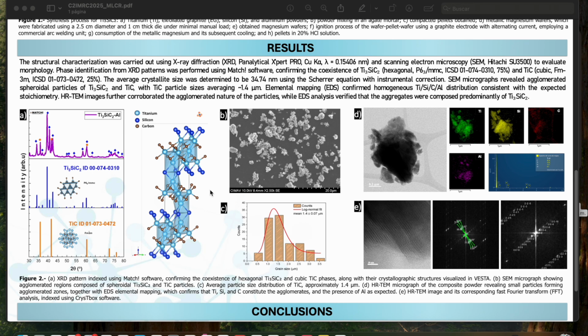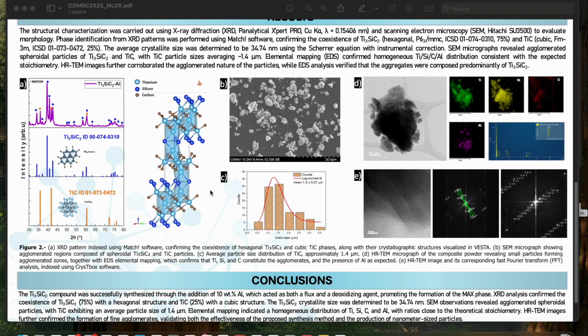stoichiometry. The mechanistic interpretation is that Al acts as both flux and deoxidizer, while Mg supplies the exotherm and reduction potential. Aluminum lowers local melting and promotes interdiffusion that favors MAX nucleation, while it also scavenges oxygen that would otherwise stabilize parasitic phases. The magnesium wafers ensure intimate reactive contact and high activity, and the CO2 sweep manages gas evolution without acting as an oxidant under these conditions. The residual TiC is attributed to carbon activity and brief overtemperature excursions during ignition.